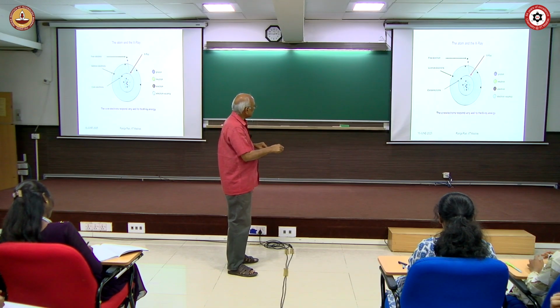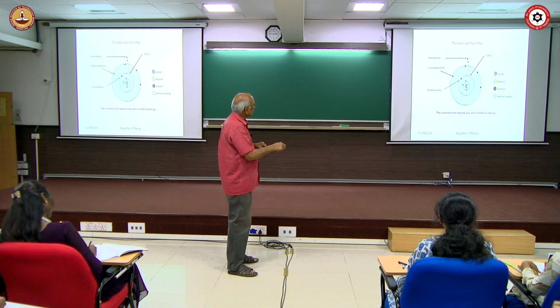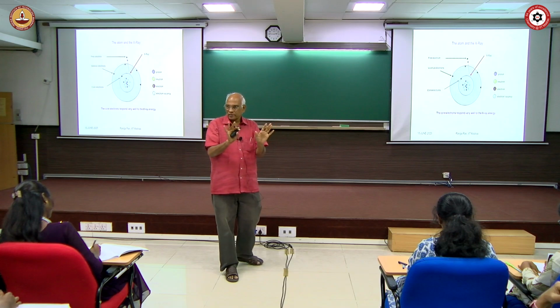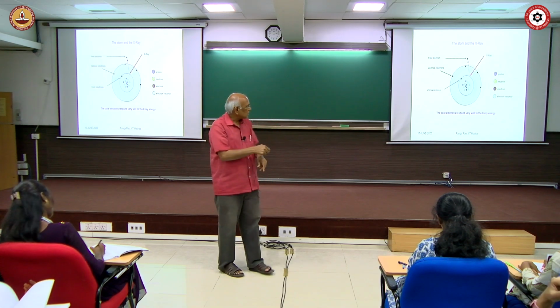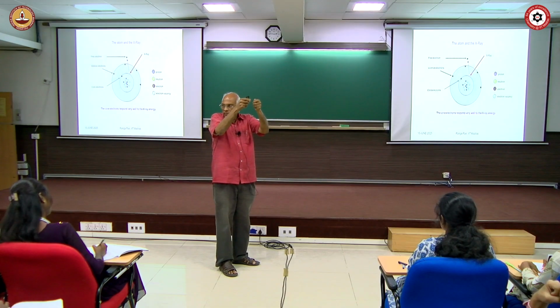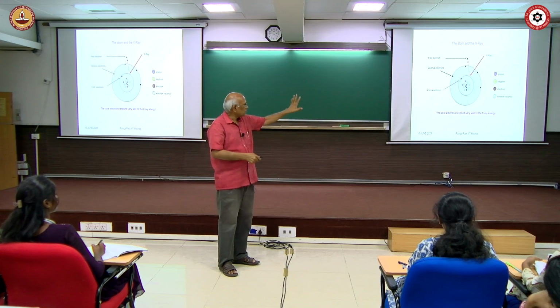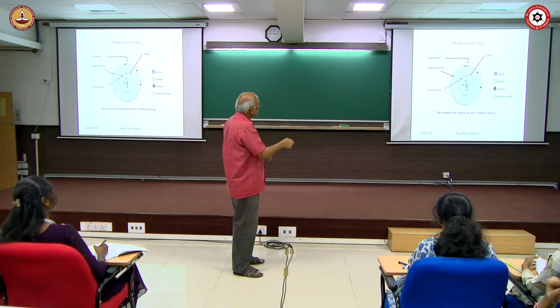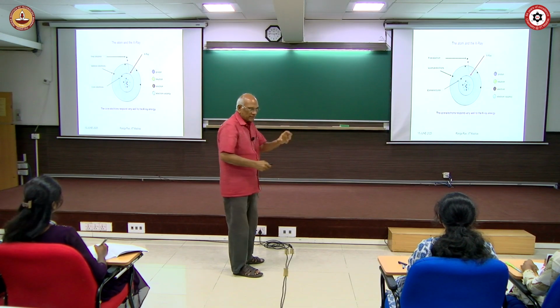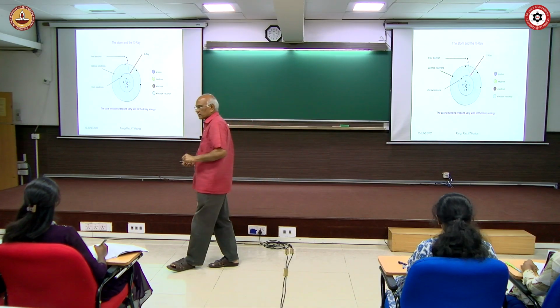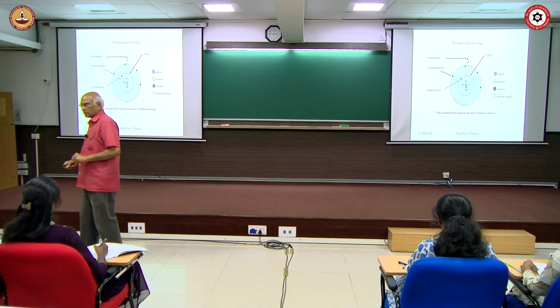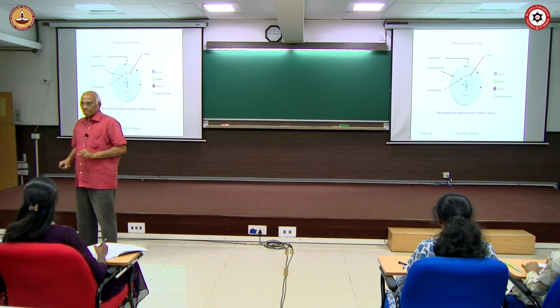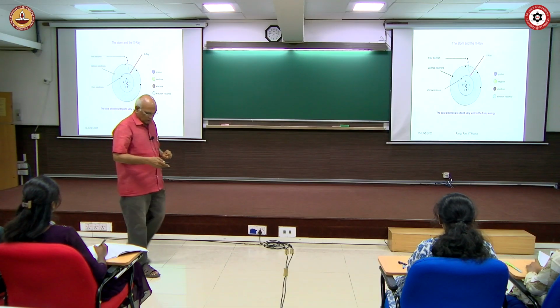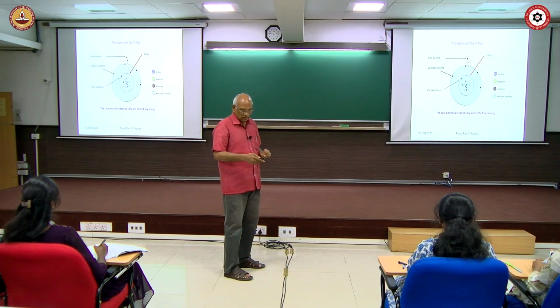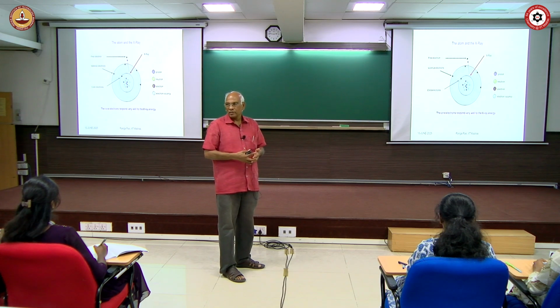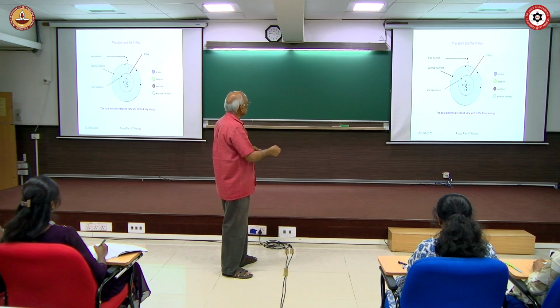Okay, so the X-ray comes here, it knocks out the electron, and this electron will come out of this atom. This is the atomic picture, but if it is in a solid, this electron which is coming out will have to go through the solid. This is only a single atom we are looking at. Now this free electron, if you can catch it and measure its kinetic energy, you can actually measure that using an analyzer. There are electrostatic analyzers which will help you to measure the kinetic energy of this free electron.